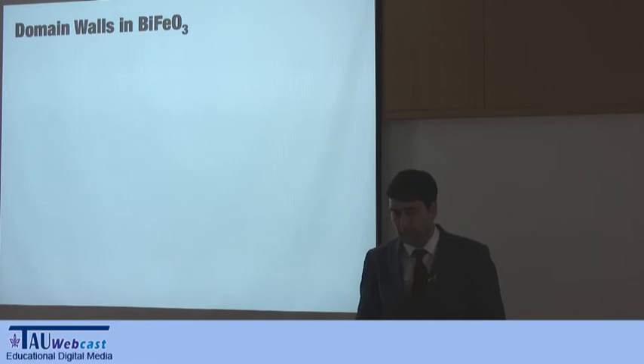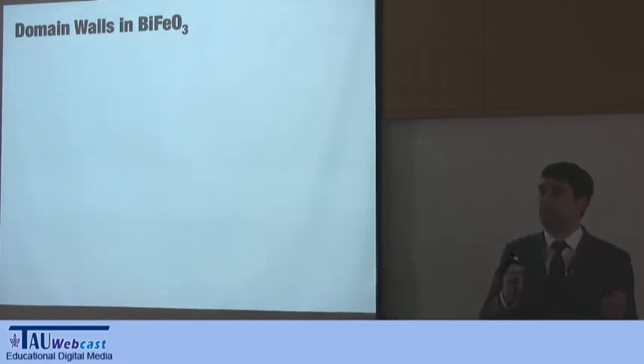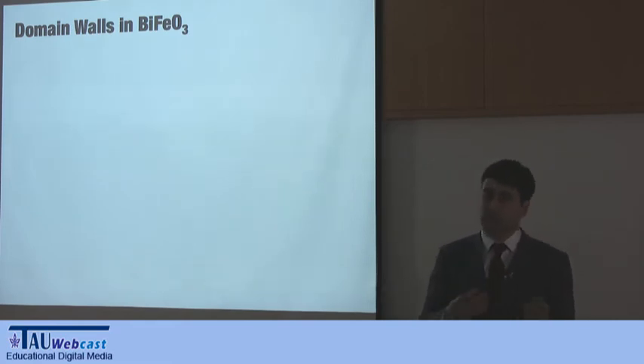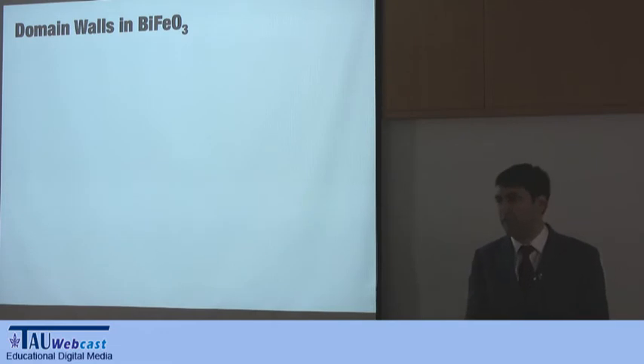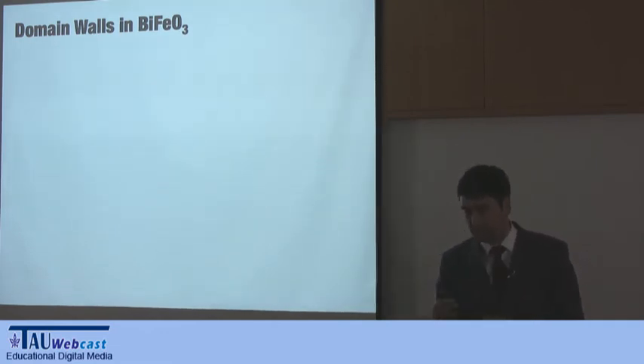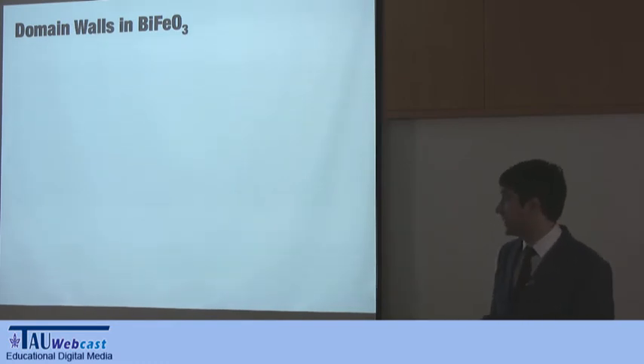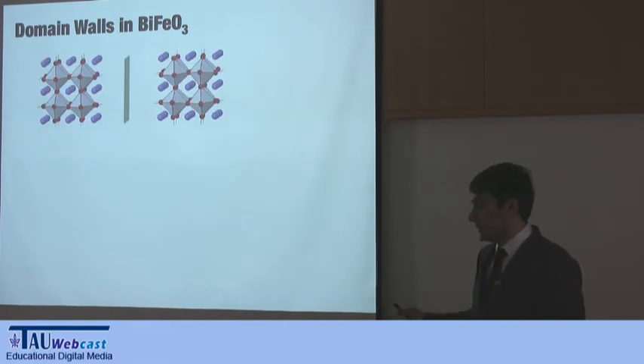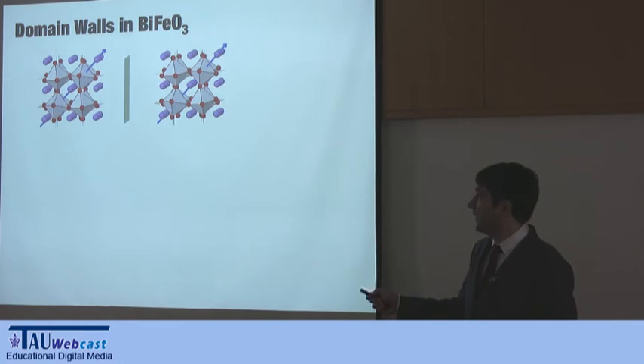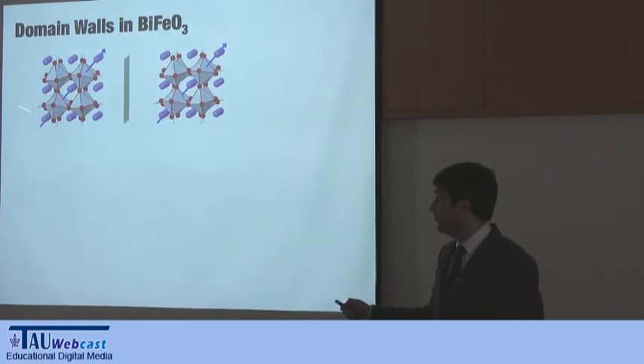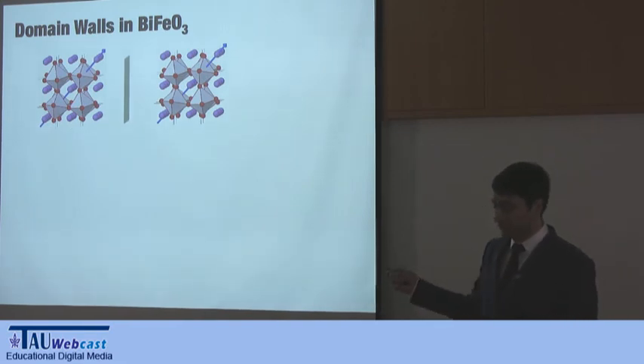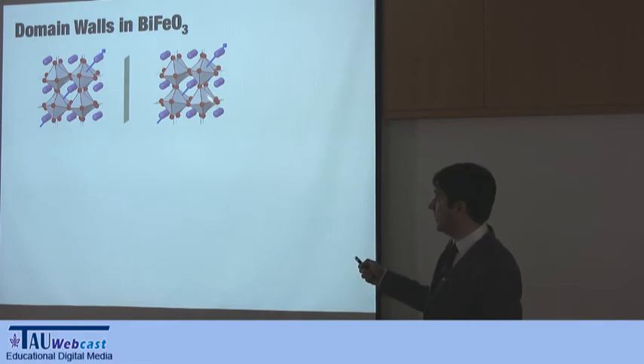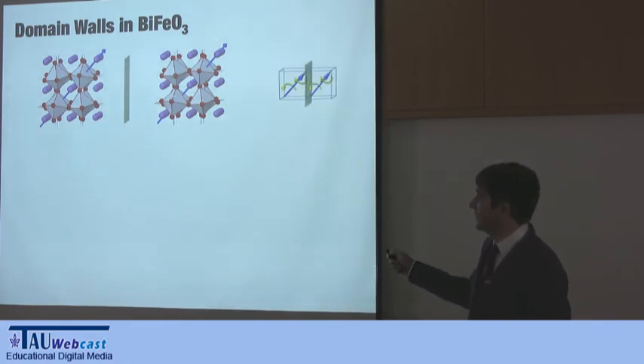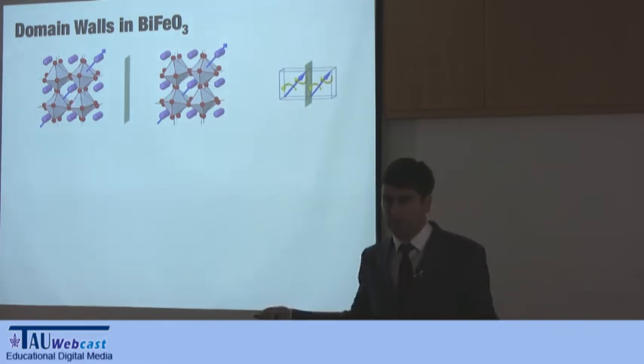One hypothesis that people put forward was that at the domain wall, the atoms rearrange. Because they rearrange, the electron levels also change, and maybe the band gap closes, so the electron levels get closer to each other, and there is conductivity. This we can check with density functional theory to see how much these structural properties changed and what happened to the electron levels. For this, you have to model domain walls. So you will have a domain wall, and to one of the sides there will be your bulk, and to the other side there will be maybe your bulk, and if they are exactly the same, the solid material, then you have just the whole solid. There is no domain wall there.